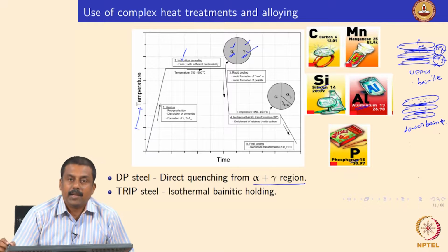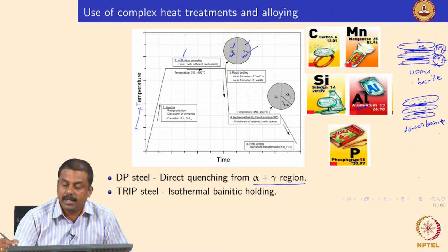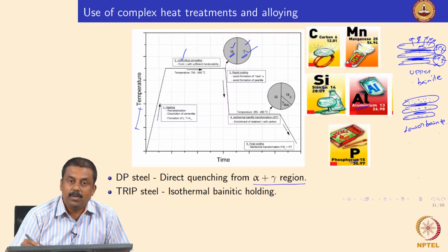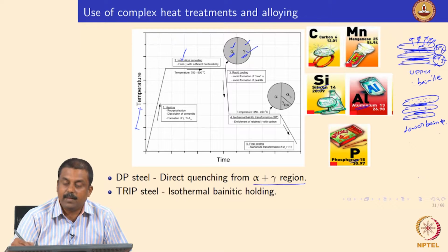Okay. So, if cementite is suppressed during the formation of bainite, when austenite is transforming to bainite, first ferrite nucleates, right. Ferrite forms and then the carbon atoms try to go out of the ferrite, but because of the extremely low solubility of silicon and aluminum in cementite... what do I mean by solubility? The cementite lattice cannot keep the silicon and aluminum atoms.